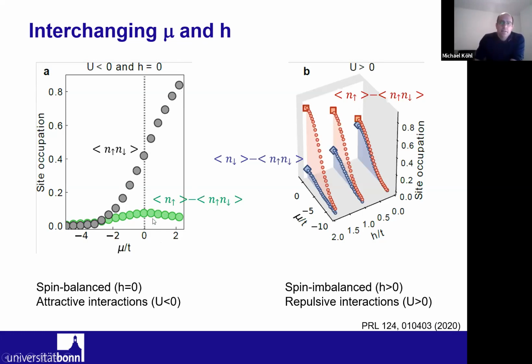And you see here at mu equals 0, the singles, they peak. That is a consequence of the particle-hole symmetry. And we see that for attractive interactions, we have way more doubles than we have singles, of course. So this would be the case where we have a spin balance and attractive interaction. So the Zeeman field is 0, and the interaction constant U is smaller than 0.